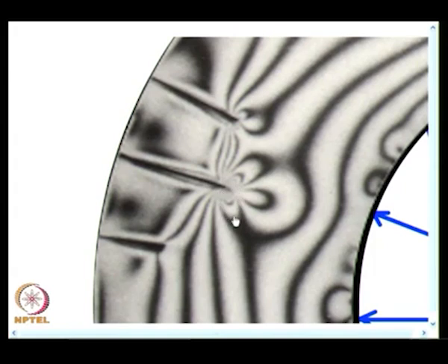You have fringes forward tilted, they are symmetrical about the crack axis, but this crack exists in a pressure vessel and stresses are very high in this region. So, the crack tip is in a stress concentration zone and the crack is also very long, and what you find, you have a prominent frontal loop, you have many such loops available in addition to the forward tilted loops.